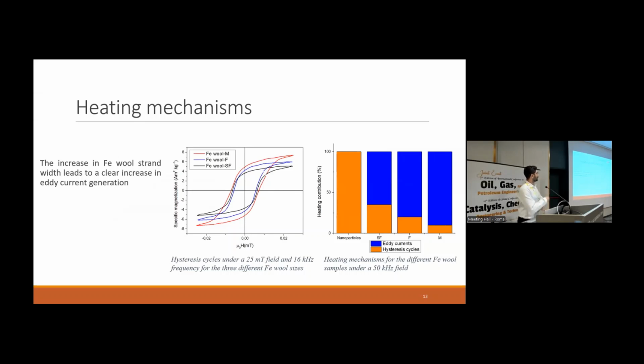After that, as I said, we mainly are going to have two heating mechanisms, either the eddy currents or hysteresis. And since we did some hysteresis loop measurements and total heating measurements with the calorimetric measurements, we are able to identify which mechanisms are dominant in our samples. And here, for example, just to verify that our measurements were correct, we took some nanoparticles. And in nanoparticles, we should be observing 100% of heating from the hysteresis cycles. And that is what we observed in our measurements.